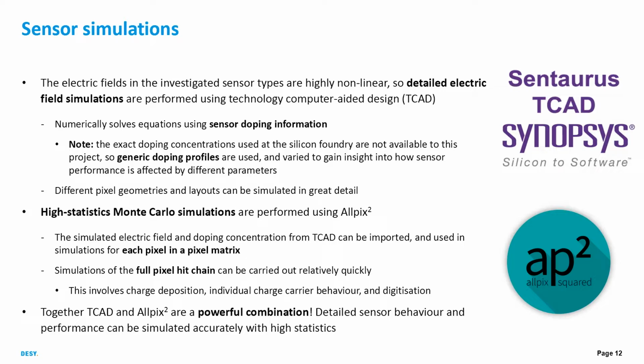In this way, we can test different pixel geometries and layouts in great detail. However, TCAD is very slow at simulating particle hits, and this is where we instead use the Allpix Squared framework to get high statistics Monte Carlo simulations. Now, the Allpix Squared simulations take the output of the TCAD, so the electric field and the doping concentration, as input, and then use it to simulate each pixel in a pixel matrix. So in this way, we can do simulations of the full pixel hit chain, which is charge deposition, charge carrier transport, and also digitization. And together, TCAD and Allpix Squared are a powerful combination, so we can do detailed sensor behavior and performance simulations with high statistics, which is nice.